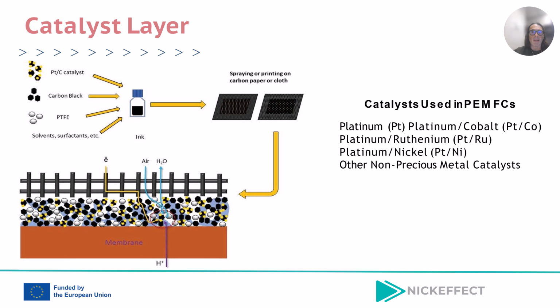The catalyst layer starts with a carefully formulated ink. This ink typically includes platinum carbon as the active catalyst, carbon black to ensure conductivity, PTFE to provide hydrophobicity and structural support, and a mix of solvents and surfactants to ensure proper dispersion. This ink is then sprayed or printed onto a carbon paper or cloth substrate. The goal is to create a thin, uniform layer that allows for efficient gas diffusion, electron transport, and proton conduction.